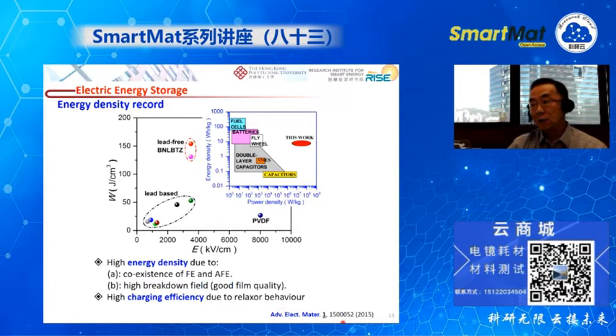This work was published a few years ago, and even up to now, this is still the record for thin film materials. We ascribe this high energy density to the coexistence of different phases, and also the very good film quality, which endows the film with a high breakdown field, so we can apply a very large electric field without breaking down the film. Also, because the film consists of a large amount of relaxor components, the charging efficiency of the device is also very high.